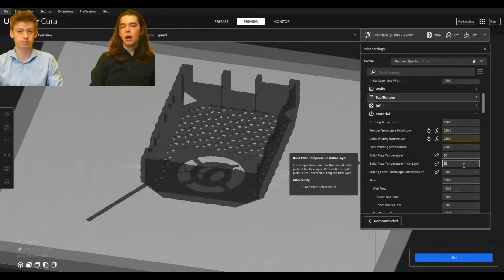constructed. The Ultimaker, for example, has an aluminum heater that heats a glass plate, and the way that heater is designed, it doesn't make very good contact with the glass plate because it's actually really flexible. And what happens is it takes the top of the glass bed much longer to get to the right temperature than if you're doing a glass bed on something like an Ender 3. I've noticed the contact is actually not super good. It seems like the corners get better contact than the center at some point.